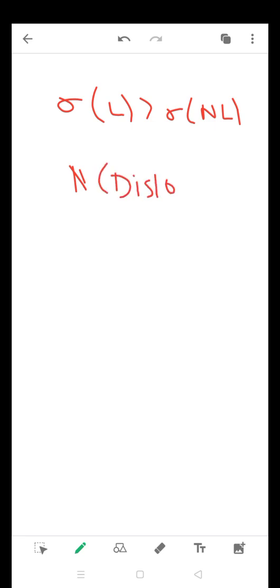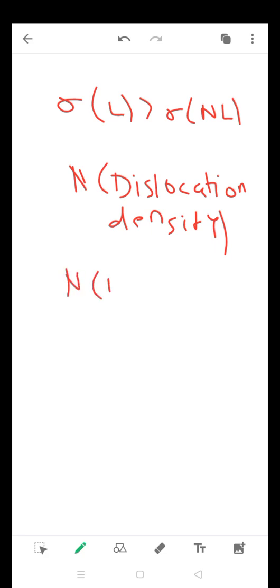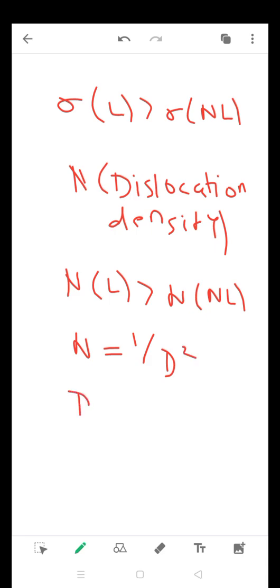Secondly, conduction was found to be higher in the case of the layered one compared to the non-layered one, mainly because of a parameter called dislocation density. Now, the dislocation density in the case of the layered joints was higher. So, N in the case of layered ones was higher than N in the case of the non-layered one, and this dislocation density N is equal to 1 by d square, where d is the crystallite size obtained from Scherrer's equation. So from XRD we first find out the d, and then from d we can find out the N value.